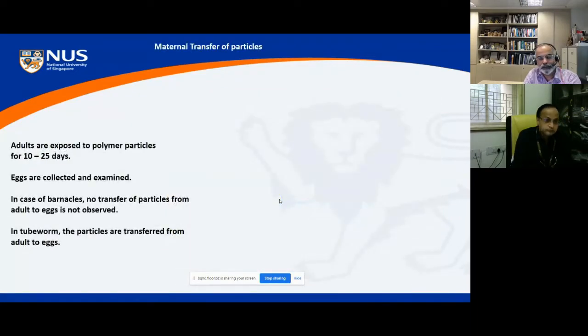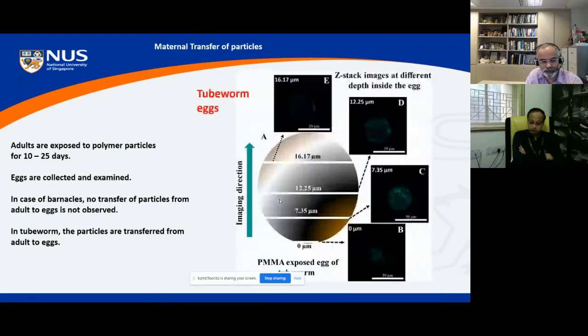Adults are exposed to polymer particles for a few days, and then we clean them up, so that we know that they are actually saturated with the particles inside their body. And then eggs are collected from them in a clean environment, right? We don't expose the eggs to the particles. So then we start analyzing the eggs. In the case of barnacles, we don't see any particle inside the eggs collected from these adults exposed to particles, right? But in the case of tube worm, they are full of them, right? So I'll show you some examples.